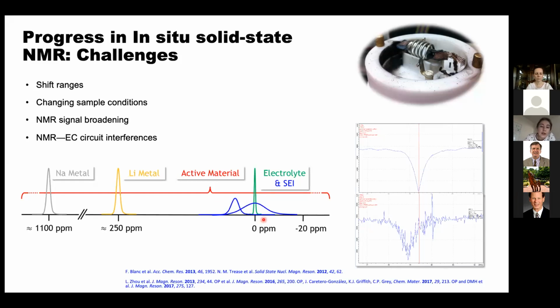And just to illustrate, around 0 ppm is where you see diamagnetic things. So they could be the electrolyte, the liquids in the electrolyte, or what's known as the SEI, which is this passivating layer that forms on the anode at low potentials. But then you have very large shifts to see the signals of lithium metal, or sodium metal in a sodium battery. And those are affected by the so-called Knight shift, which is a signature of the density of states in the metal. So these are good things, but in practice, it makes the NMR detection more difficult because you've got to be able to sweep these very large ranges.